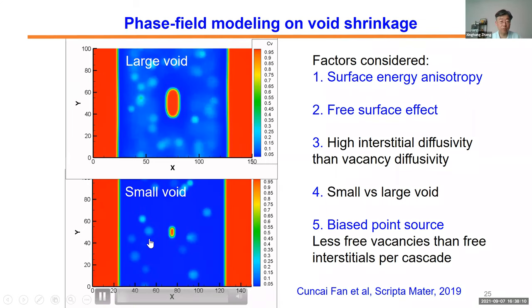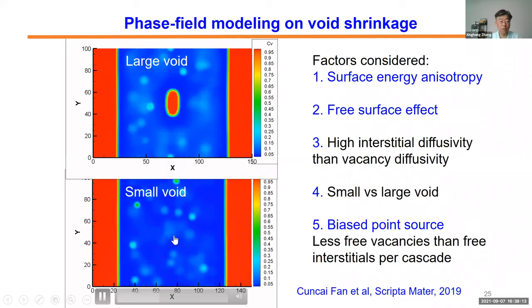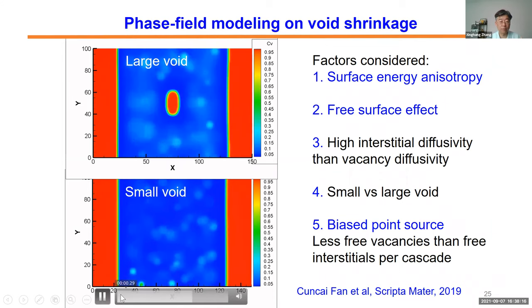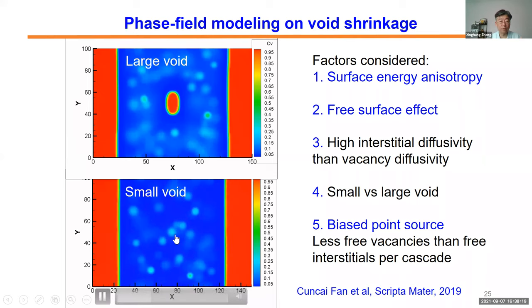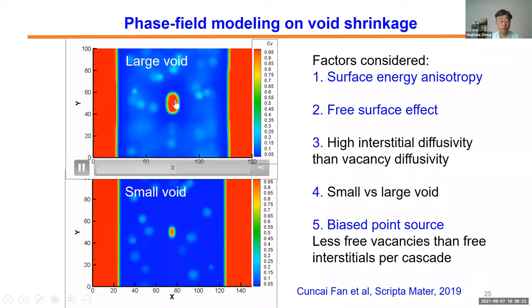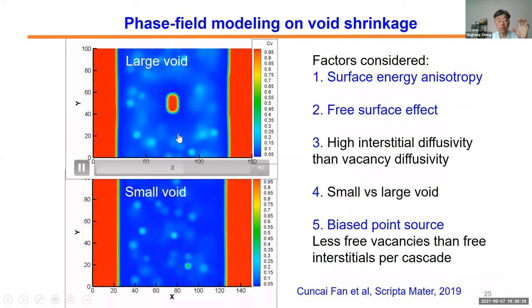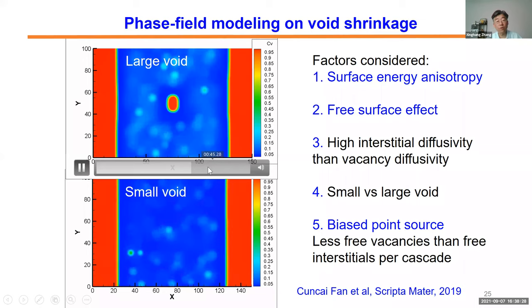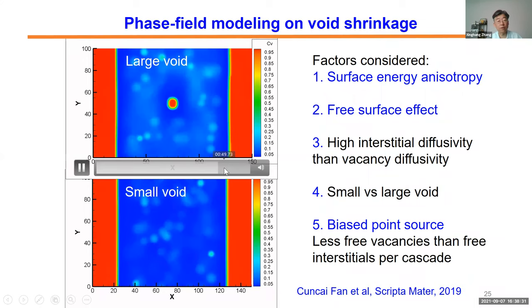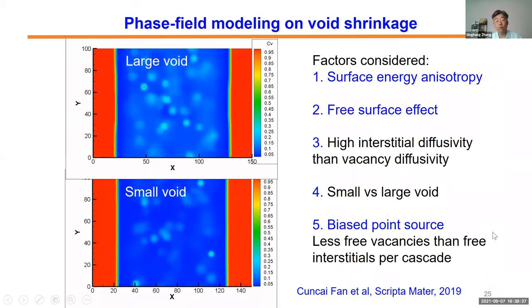But if you look at this same radiation on the small voids, these small voids quickly spheroidize and then disappear. This video is very fast for the small voids. But for the large voids, this is a very slow process. So this void is still surviving after long times of radiation. But eventually, what you're going to see here is this void is also spheroidized. And after they spheroidize, then they shrink quickly. So what this shows us is basically radiation-induced biased defect flux, meaning interstitials preferentially get to the voids and lead to the filling up of the nano voids, in this case for copper.